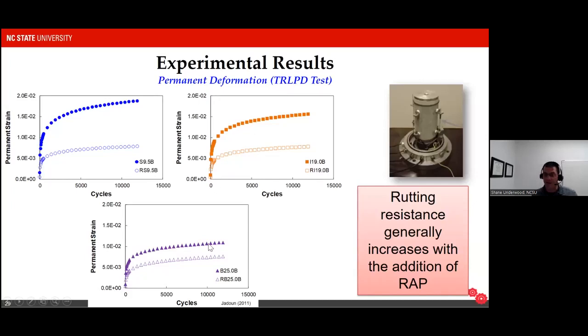So let's step back for a moment. The experiments show us that for these particular materials, when we add RAP, the material gets stiffer, more resistant to permanent deformation and possibly rutting. But the counter is that they're possibly more likely to crack when they're used in service.